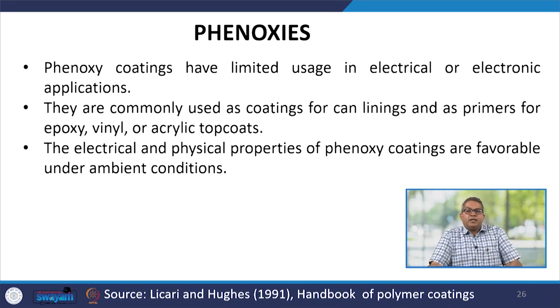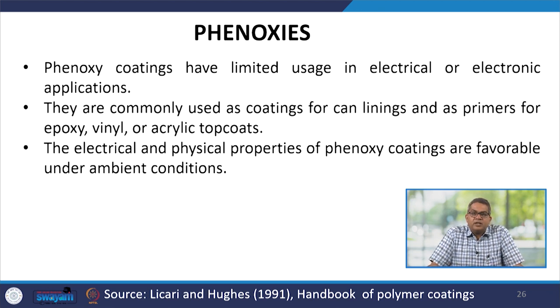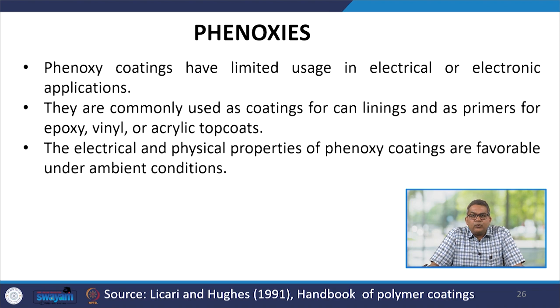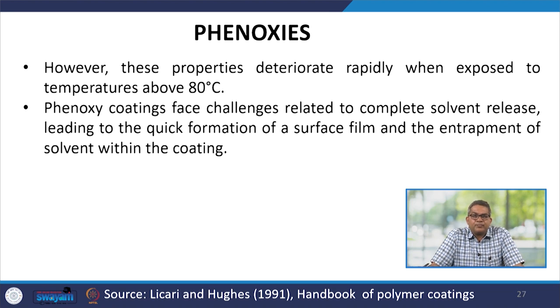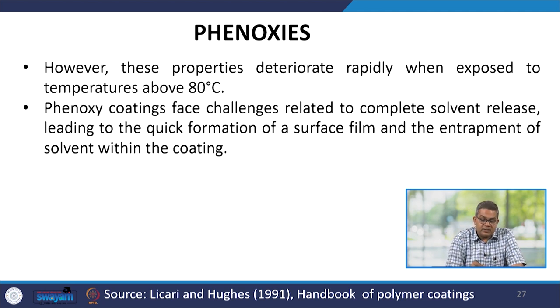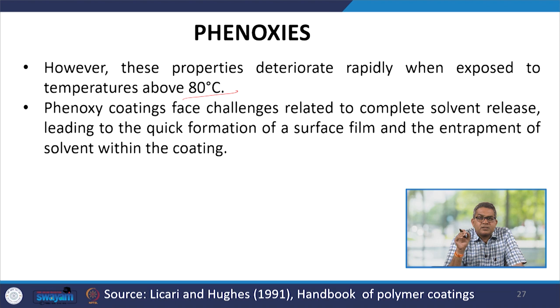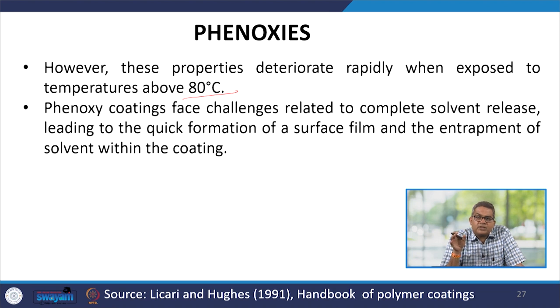Coatings with methyl ethyl ketone solvent dry very fast due to the low boiling point of that solvent. Phenoxy coatings have limited uses in electrical or electronic applications and are commonly used as coatings for can lining and as a primer for epoxy, vinyl or acrylic topcoats. Electrical and physical properties of phenoxy coatings are favorable under ambient conditions, but deteriorate rapidly when exposed to temperatures above 80°C. Phenoxy coatings also face challenges related to complete solvent release, leading to quick formation of a surface film and entrapment of solvent within the coating.